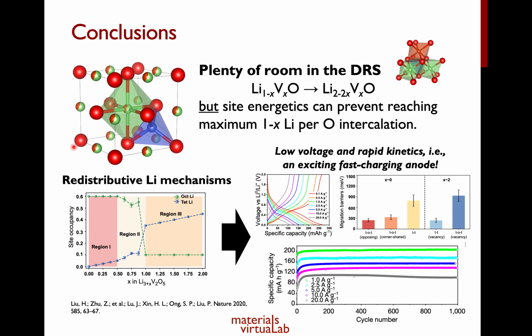The second thing that I want to communicate is that in this disordered rock salt, you have a very, very interesting redistributive lithium mechanism, okay. When you start inserting additional lithium, initially you have a very simple increase in occupancy in the tetrahedral site, but at some point, the entire lithium distribution redistributes between the octahedral and tetrahedral sites, and that redistributive process actually results in low voltage and rapid kinetics, okay? In other words, a very, very exciting fast charging anode that we believe holds great potential for commercial applications, okay?